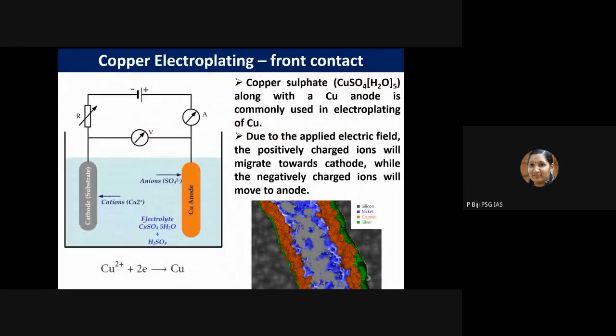Then your next target is to deposit the actual conductor, that's copper electroplating. Initially, after electroless plating of nickel, you need a sintering process. I already told you that nickel silicide has to be formed, at a temperature of almost 300 to 400 degrees Celsius. After that, you need to deposit copper. So copper generally will be electroplated as the front conductor.